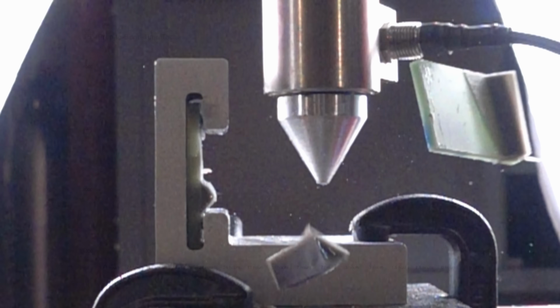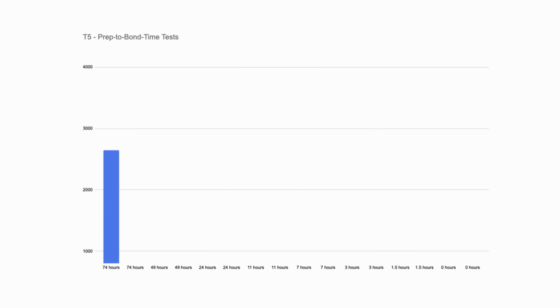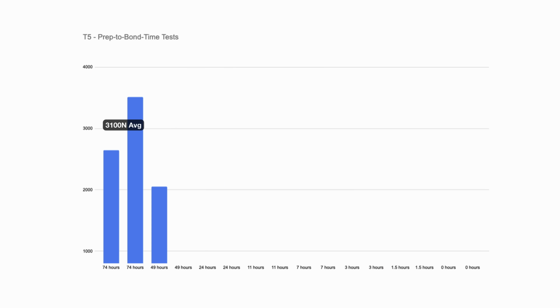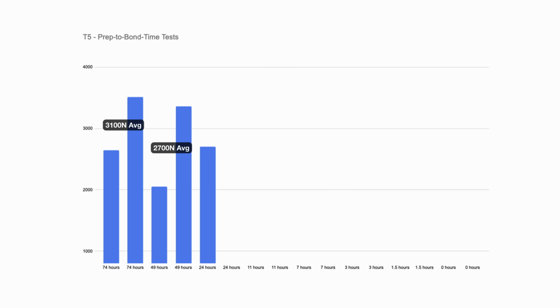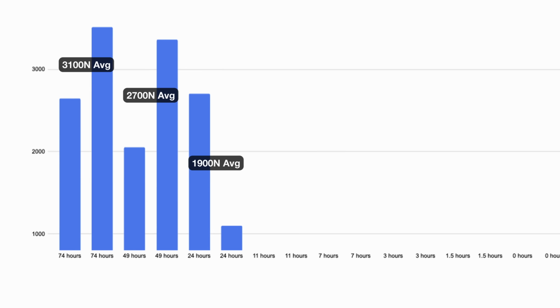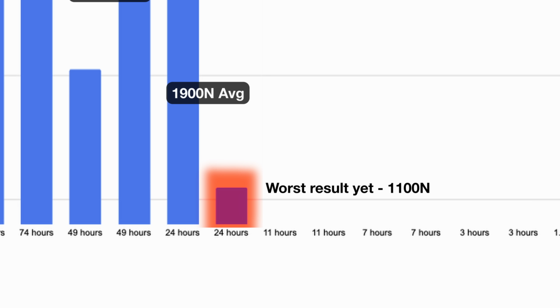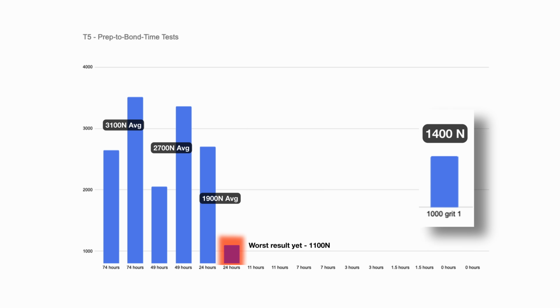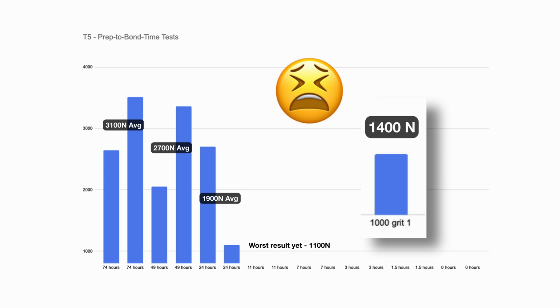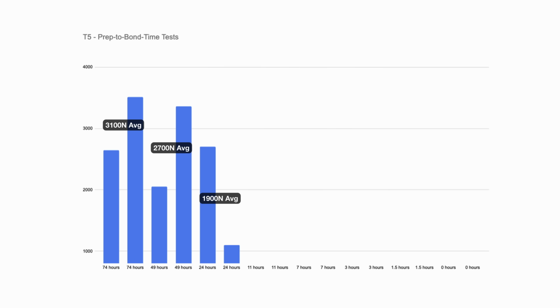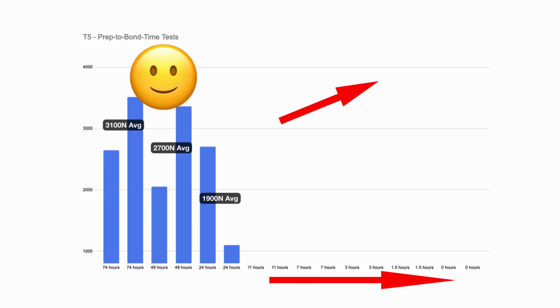All right, at 74 hours, we've got 2600 and 3500, averaging 3100 newtons. At 49 hours, we have a wider split with an average of 2700, and at 24 hours, we have an extremely wide split averaging 1900. That lower bound is our worst result yet at 1100 newtons, which is worse than the 1000 grit sandpaper. Ouch! If what I've heard is true, as the prep to bond time goes down, the strength should go up. So it makes sense to me that these early results aren't great, but let's keep going.